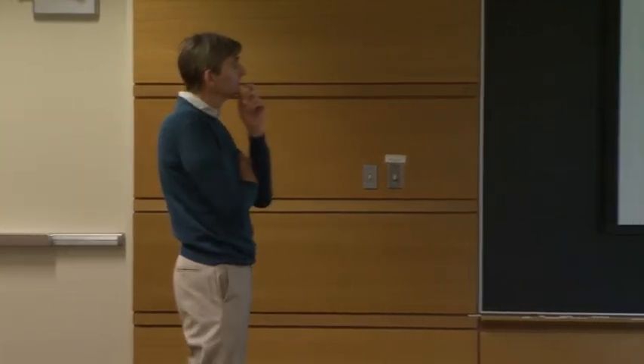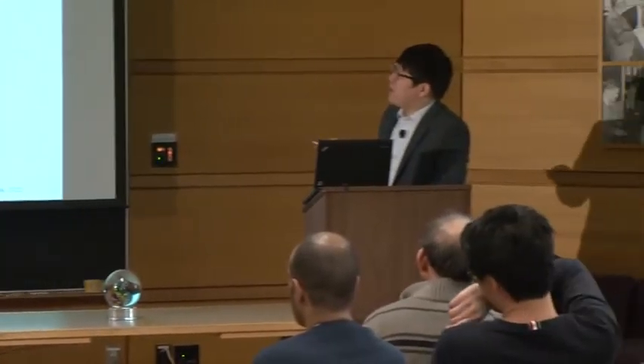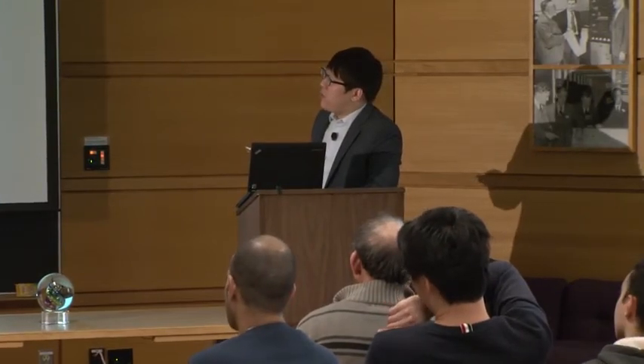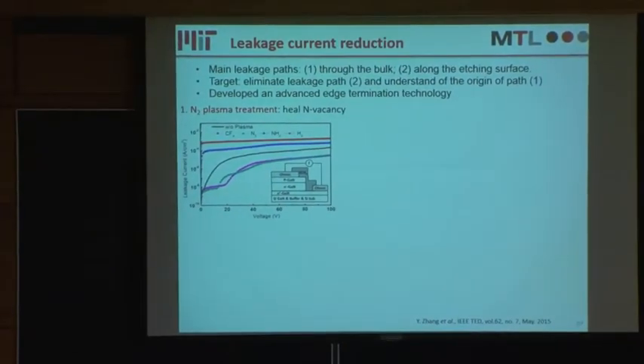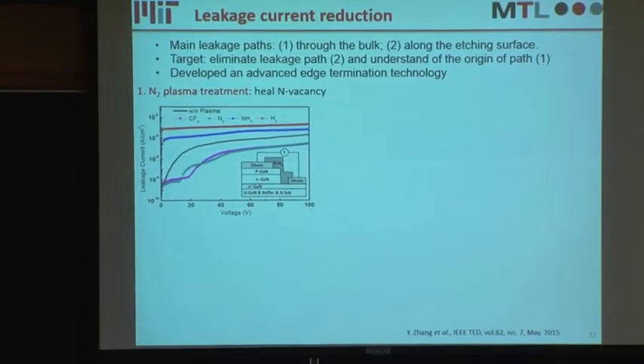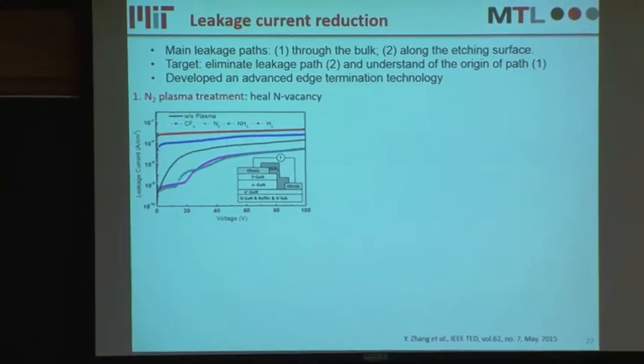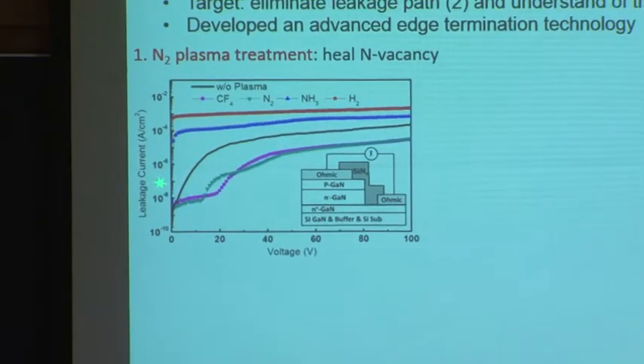We think the improvement mainly comes from healing the nitrogen vacancies, because we actually utilize two treatments - one is nitrogen, the other is hydrogen. It has been reported that hydrogen plasma treatment creates a lot of nitrogen vacancies, and nitrogen heals these vacancies. So here we can see this is without any plasma treatment. If we have hydrogen, we have several orders of magnitude larger leakage current. If we have nitrogen plasma treatment, we have lower leakage current. But I think more detailed material characterization at the microscopic scale would also be very helpful for the next steps.